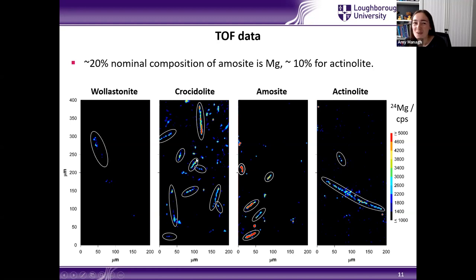Rather surprisingly though, we did see magnesium within crocidolite, even though it isn't within its nominal composition. Sometimes when you get asbestos fibers found in nature, you do get other elements that have been substituted into their structure, which is what we think we're seeing here. So this was a little bit of an unexpected finding to find so much magnesium within the crocidolite sample.